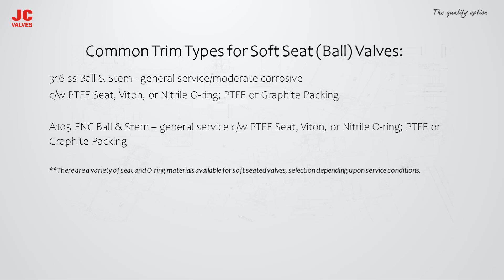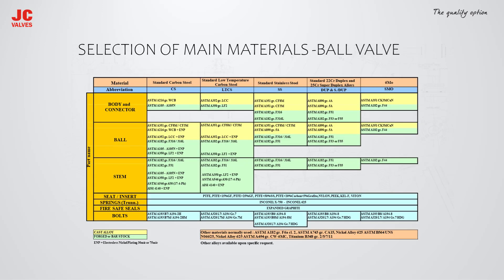These coatings are usually very hard and highly corrosion resistant. Regarding non-metallic trim materials, the most common is polytetrafluoroethylene, or PTFE. Pure PTFE is very soft and pliable and forms a great zero-leakage seal when combined with a smooth metallic mating surface. However, pure PTFE has proven to be too soft for many valve applications, so various reinforced PTFE materials have been developed, including additional strengthening materials such as glass, carbon, or graphite.